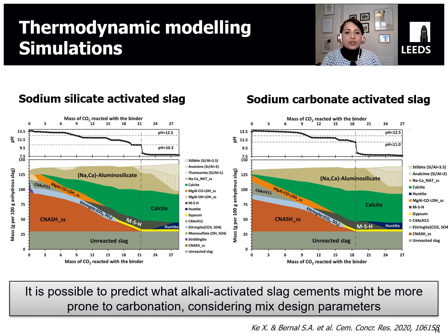So we did some thermodynamic modeling. We continue working in this area. These are some thermodynamic modeling simulations of carbonated sodium silicate and sodium carbonate activated slag cements. And I will say at the time these were the closest to what we were seeing in experiments in terms of simulations that we could produce, which I think also enable us to understand more and more about how things happen.